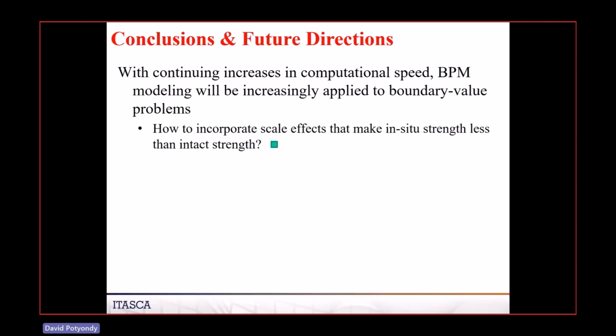What you find is that if you're doing, for example, a compression test, you need to have a certain minimum number of particles across the diameter. And once you have that many, and that might be 15 to 20, if you add more and more and more, you still get the same answer. So it's like you have to have a representative volume, which is obvious, right? If I'm doing a compression test in 3D on a bunch of bonded particles, if I only have 2 particles across the width, there's not enough resolution in there to have a representative volume.